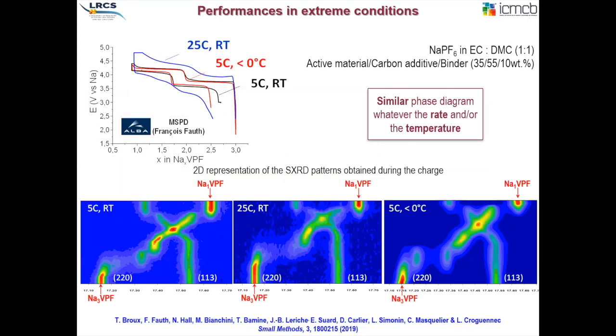What we did as well was to investigate the structural properties of this compound under various conditions in terms of electrochemical cycling. Thanks to the very bright source in the Alba synchrotron and to our operando cells, which perform pretty well, we were able to cycle this compound up to 25C in the synchrotron and identify indeed that the phase transformations still occur even at this very, very high rate and with intermediate phases spotting here.